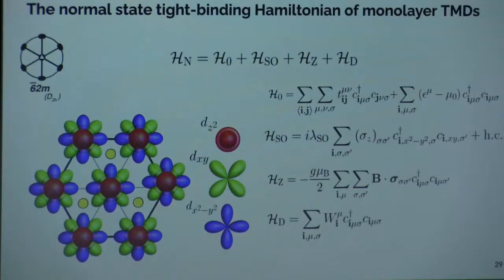But all of this is related to spin physics. Now, let me go to the complex model, which is necessary to capture how the system responds to impurities. So we cooked up a tight binding model considering all the niobium atoms. Each niobium atom has 3 d orbitals. For simplicity, I will refer to the orbitals as the red one, the green one, and the blue one. The first term are the hoppings. The second term is Ising spin-orbit coupling, which stems from the in-plane green and blue orbitals.